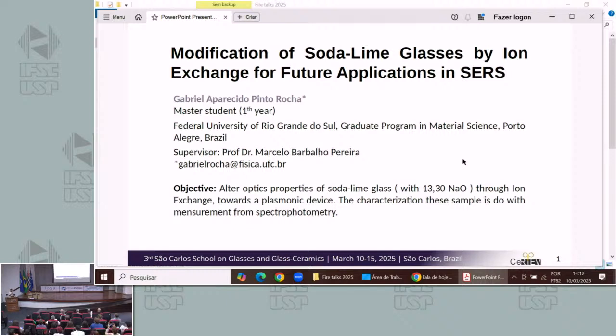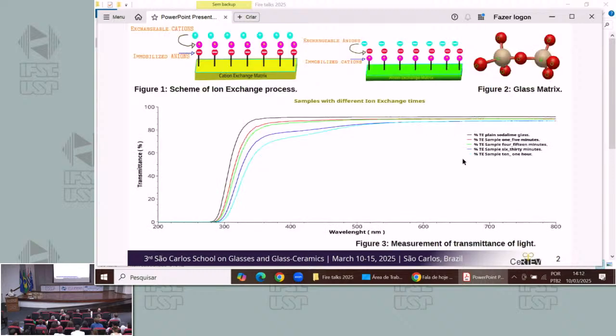I work with soda-lime glass, which is composed of silicon oxide, calcium, and sodium. My goal is to modify the optical properties using ion exchange. This technique consists of replacing ions present in the structure with others that are in a molten salt solution. Since the new ions have different polarizability than the original, the process changes the refractive index.